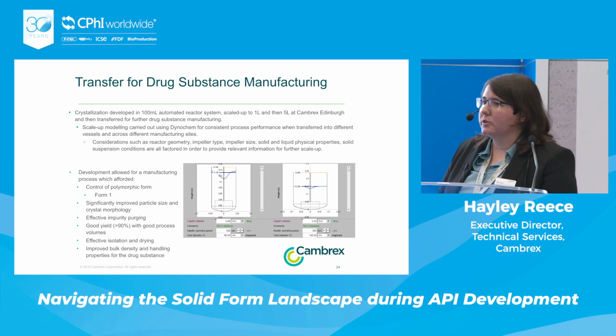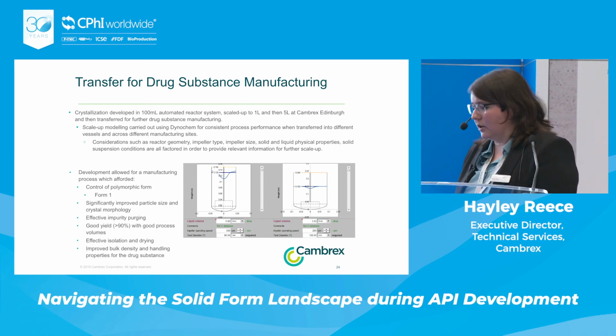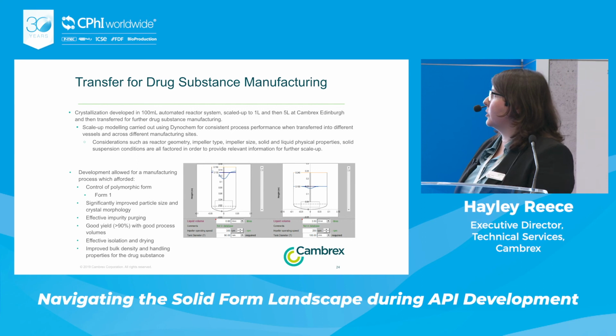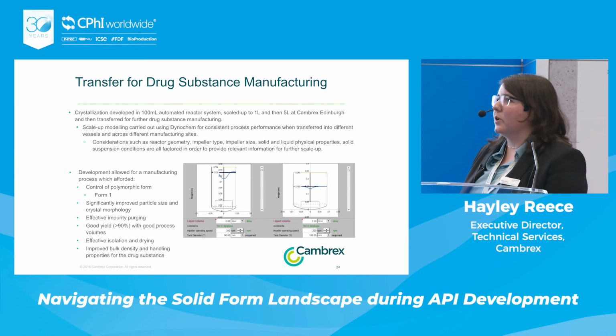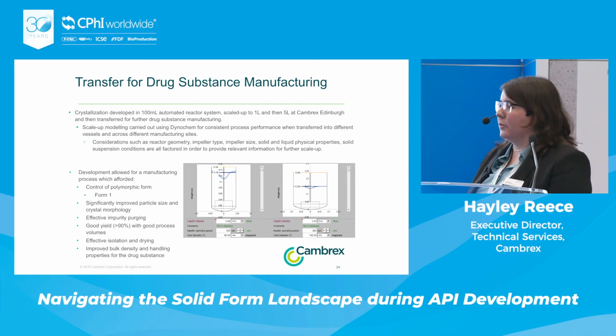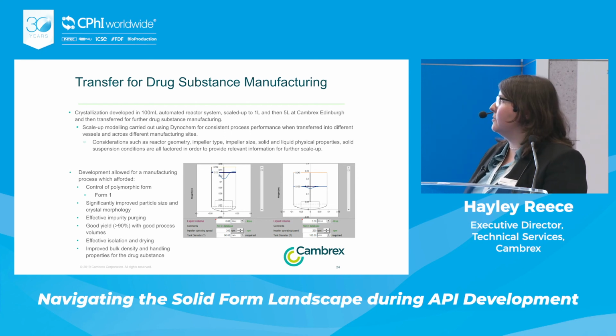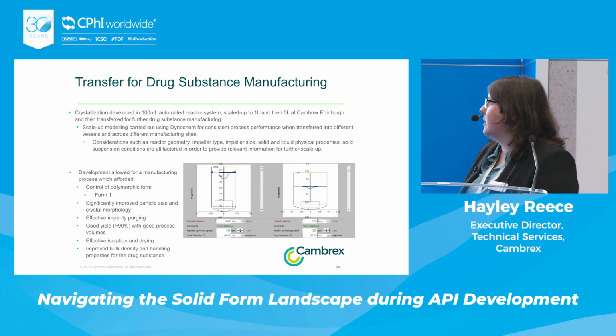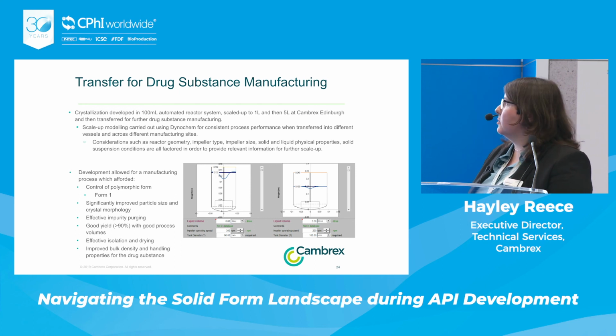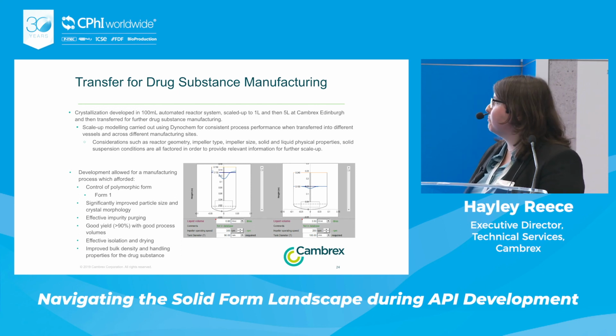So from this process, we were able to get a manufacturing procedure for the crystallization that favored form 1. So we never saw any of the hydrates at any point during the further crystallization development, because we were operating in the favored form 1 zone or operating space. We also significantly improved the particle size and the crystal morphology. So this allowed for better filtration rates as well as handling of the actual crystalline material.